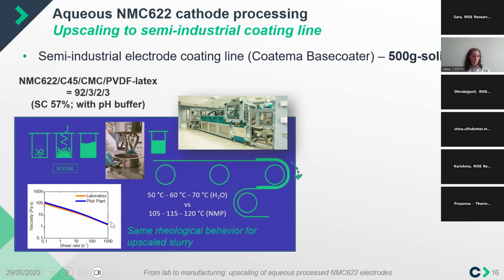This is the shear thinning behavior that we look for. For water-based slurry, sometimes it's more difficult to get this nice, continuous slope.